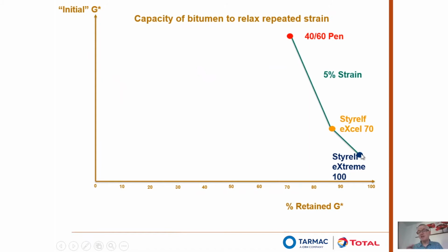So that's showing it's very elastomeric and resistant to strain. It's still, after 30 minutes, capable of relaxing the strain that's been applied to it. The Styrelf eXcel 70 is possibly not quite as good, but still reasonably good. And the 40/60 Pen, not particularly elastomeric at all, is still, after 30 minutes, retaining about 70% of that initial stiffness. So at 5%, very low levels of strain, we can see that picture.